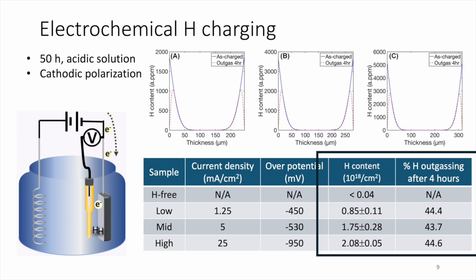As the sample we use is very thin, we can use a 1D diffusion model for this hydrogen ingress process. And we can, based on Fick's law, calculate the hydrogen distribution and hydrogen profile like this. On the surface, we have a good amount of hydrogen, and in the middle, we have almost no hydrogen. Well, you might wonder, why don't you charge through?